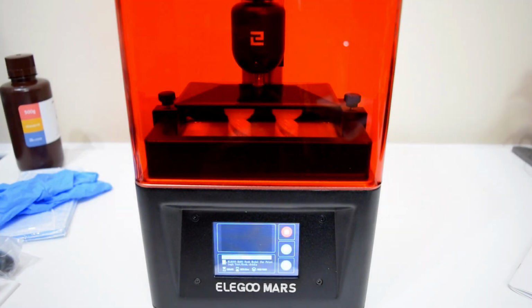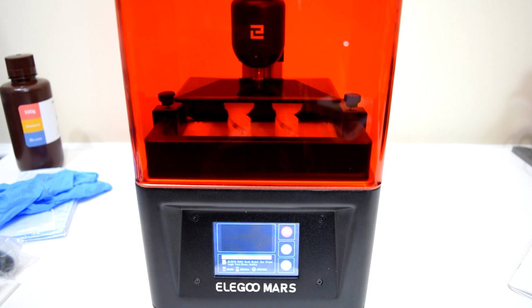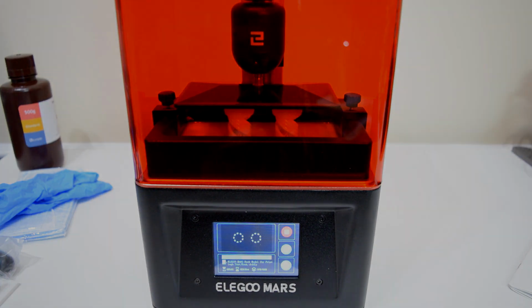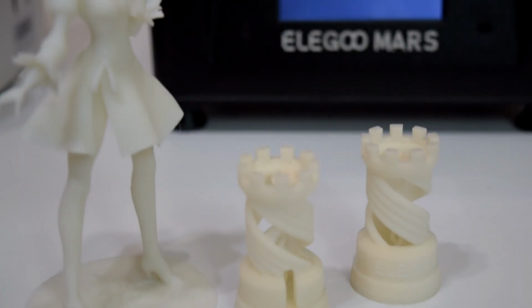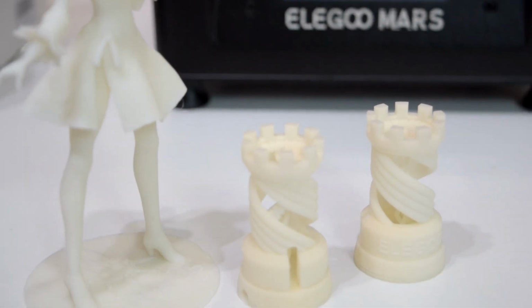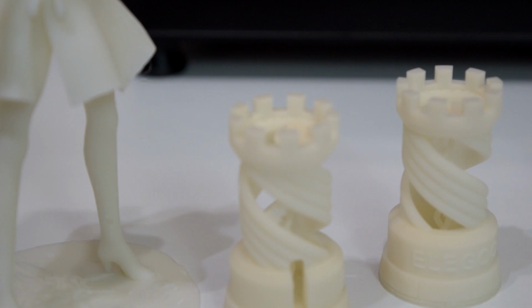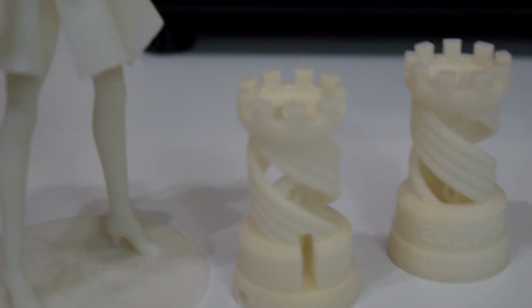Apparently some resins stay very UV sensitive even after they've cured into a hard plastic. For example, after printing the Rook test print that came on the USB drive in white Elegoo resin, I decided to set those prints in my windowsill for a few hours in direct sunlight to cure. You can look at the difference between those Rook models and this 2B model I printed and let cure for about 20 minutes. The Rook is drastically yellower and on its way to a brown color.